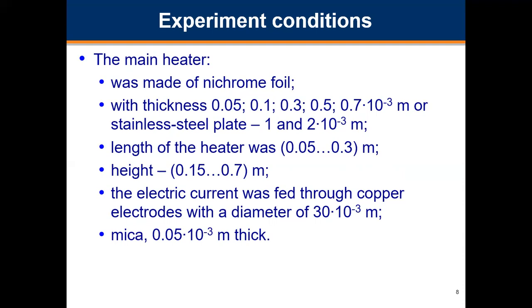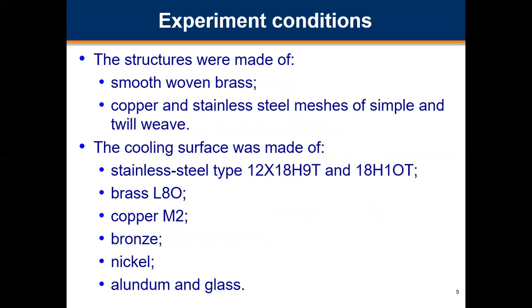A layer of mica, 0.05 times 10 to the negative 3 meters, acted as electrical insulation between the wall and the nichrome. Radiant heating and surface heating by direct passage of alternating electrical current through the wall and the adjacent porous structure were also used. The structures were made of smooth woven brass, copper, and stainless steel meshes of plain and twill weave and consisted of 1, 2, and 3 layers.